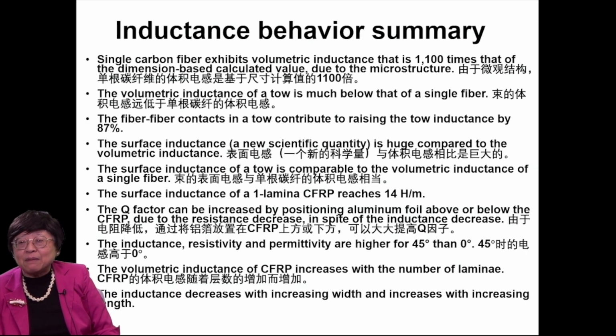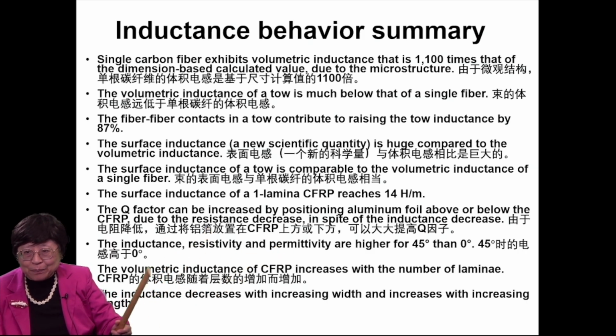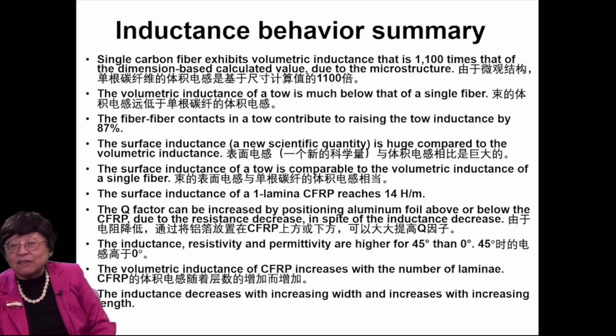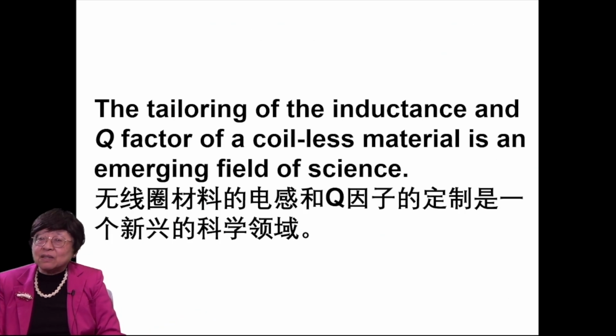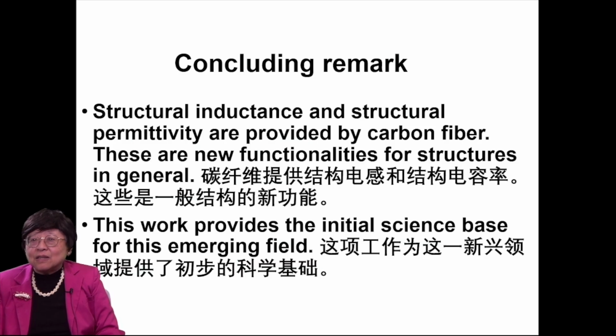The inductance, resistivity, and permittivity are higher for 45 degrees than 0 degree. And they are not independent of one another. Okay. The volumetric inductance of CFRP increases with the number of laminae, and the inductance decreases with increasing width and increases with increasing length. The tailoring of the inductance and Q factor of a coilless material is an emerging field of science. So structural inductance and structural permittivity are provided by carbon fiber. These are new functionalities for structures. And this work provides the initial science base for this emerging field.